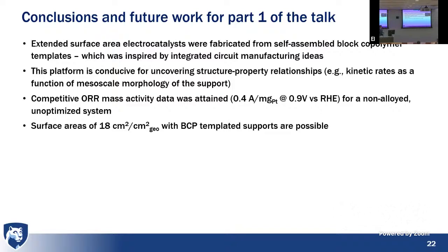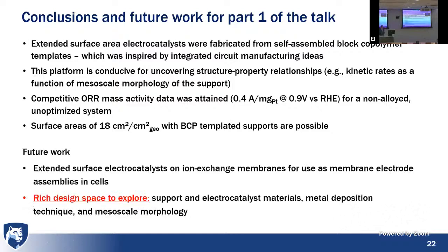We could alloy, we could get better sidewall coatings at low loadings, maybe using atomic layer deposition. And if you were to make a 100 nanometer tall structure at the same width, sub 20 nanometers, you can get to 18 centimeters squared per geometric area. 3M was 8 centimeters squared. So we think this is possible, but yet to be done. And there's just a rich design space to explore.